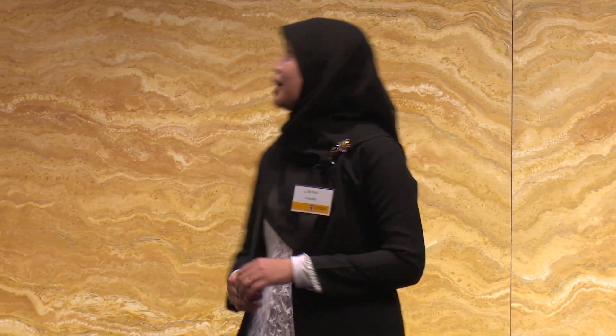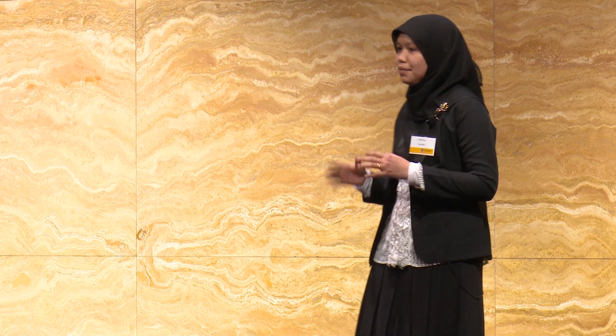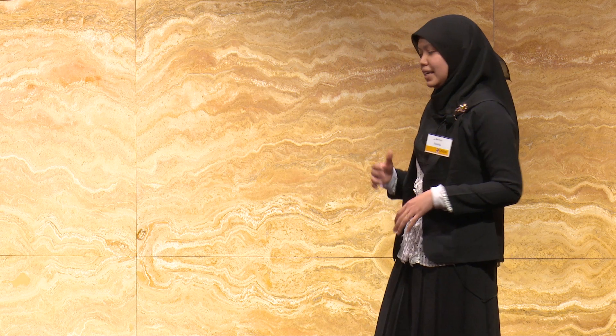So, in my research, instead of wood, I use the banana tree, because it is an annual plant and it is actually a waste — every time the farmers are harvesting the fruit, they will cut down the tree. What I did is extract the cellulose from the banana tree, reduce the size into the nanoscale, and use it for making plastic.